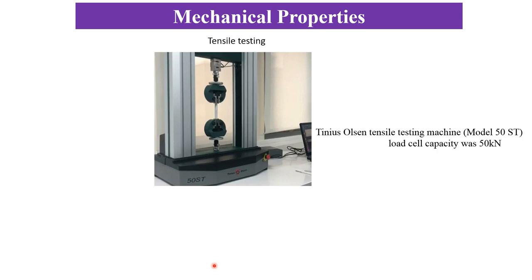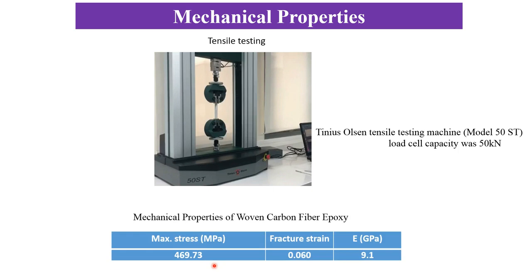The next step after fabrication was tensile testing. We performed tensile testing to calculate the stiffness and other mechanical properties of the composite plate. The stiffness is used later to determine the toughness of the material. To perform tensile testing, we use this machine, a Tinius Olsen tensile testing machine. The model is 50ST, and the load cell had the capacity of 50 kilonewton. Some of the calculated mechanical properties are depicted in this table here.